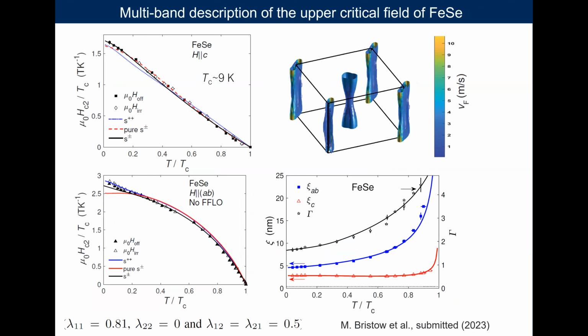We can use the multiband description, having hole and electron pockets, to try to fit the upper critical behavior, which is almost linearly dependent on temperature when the magnetic field is along the z-axis, and it has a slightly different behavior when the field is in the plane. So the parameters used to model this behavior also require that the interband interactions are much stronger than the intraband interactions. Again, supporting that S plus minus is likely a good contender for this behavior.